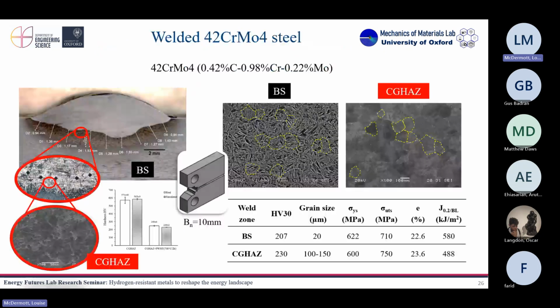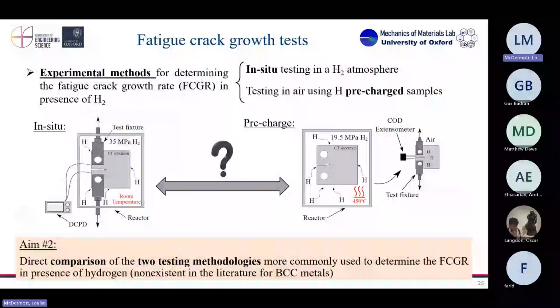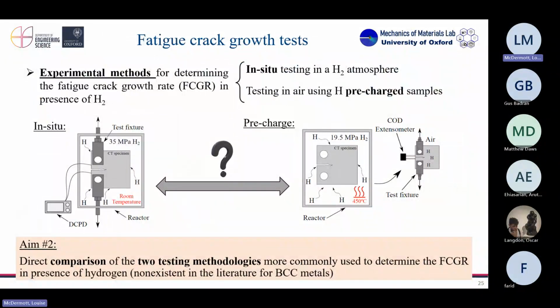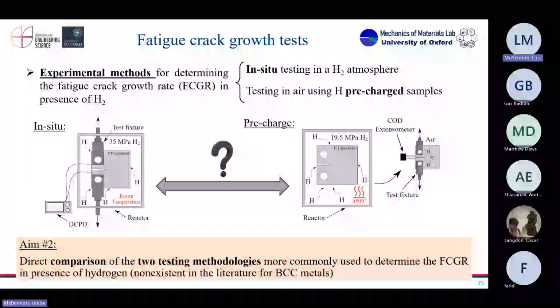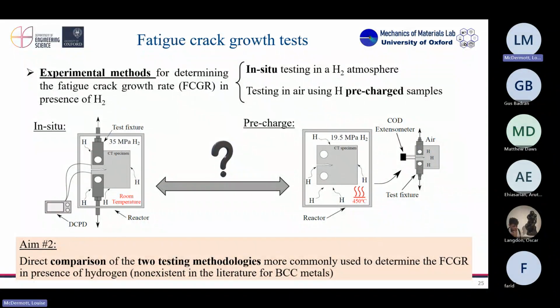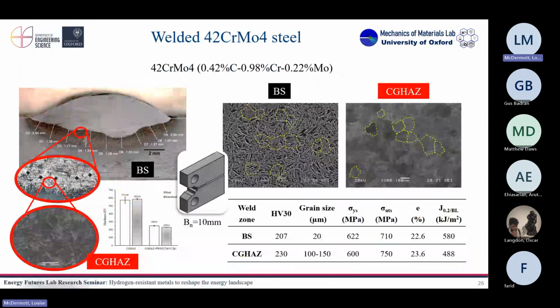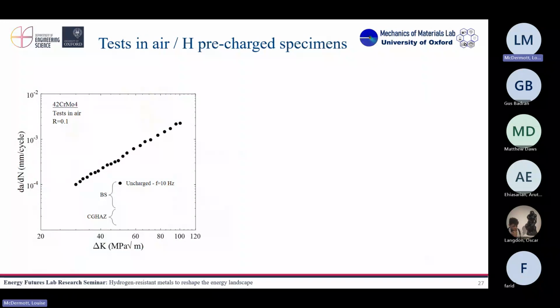I don't know if you are familiar with fracture in general or with fracture testing or fatigue testing, but basically, just to be more simple, if we have this sample, what we do is apply a load that's a cyclic load, so it follows a sine curve. So we apply that load, and basically we are pulling the sample like this. So the crack that's here, if we pull the sample, just pull and release, the crack is going to grow. And when you pull with a certain load, you create a stress intensity factor there. So what we measure in fatigue is the millimeters per cycle that the crack is growing versus this stress intensity factor range.